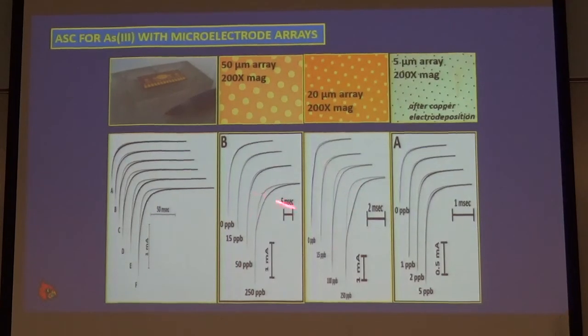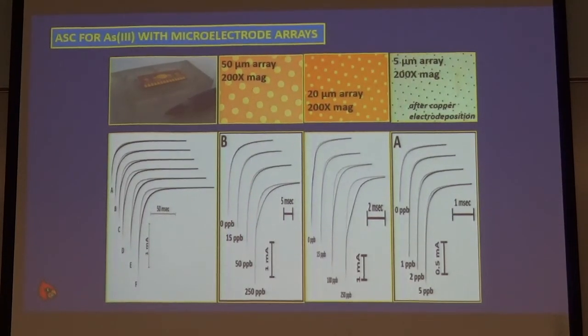I should have said the quality of these data is really quite surprisingly high. Any one of these traces here is 3 superimposed runs right on top of one another. So in the short term, it's very, very reproducible. So you can see that by going to the array, what we've done is make the 0 or the blank signal smaller, which allows us to look at smaller and smaller charges due to our analyte.